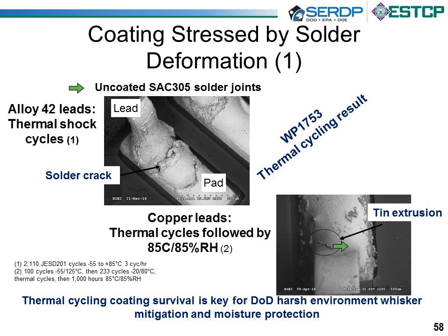And the other thing we saw is that we examined combinations of cycles, so thermal cycles followed by high humidity on copper leads resulted in some very interesting tin extrusions occurring at grain boundaries. The bottom line is that the DoD coatings need to survive some of these sorts of stresses, remain intact, and remain adhered to provide both humidity and whisker mitigation protection.